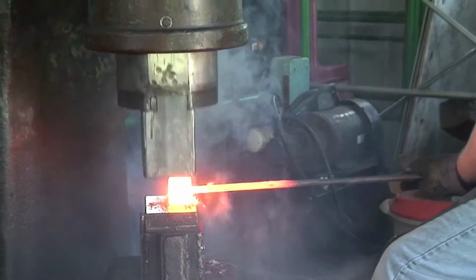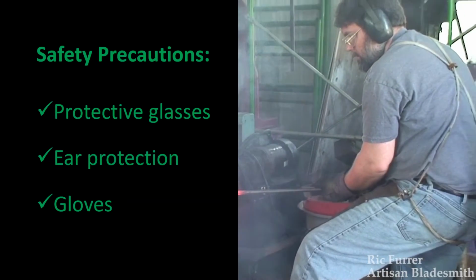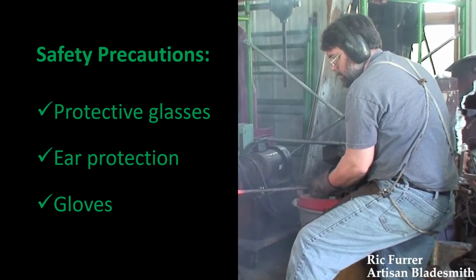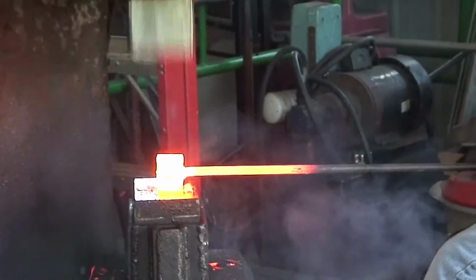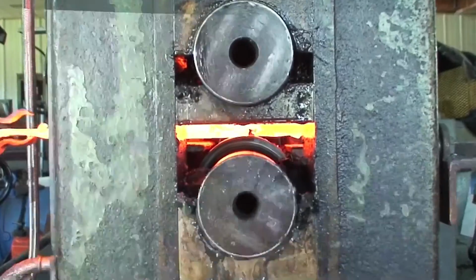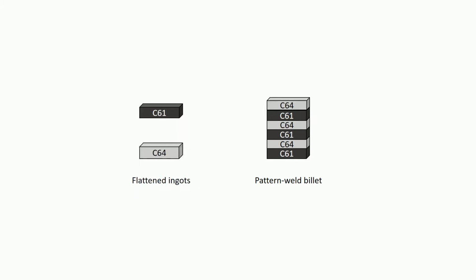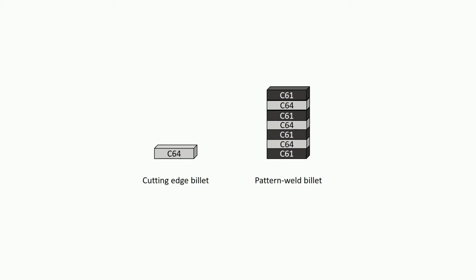To forge Dragonslayer, our artisan bladesmith, Rick Furrer, heated ingots of C61 and C64 steel and flattened them using a power hammer, hydraulic press, and roller. He then cut the ingots into 8 smaller bars, 7 to become a billet for pattern welding, and 1 bar of C64 to become the blade's cutting edge. Because of the high chromium content in Therium steels, Mr. Furrer had to devise a very unconventional method for welding the bars together. To respect the privacy of his intellectual property, we did not include further footage of the forging.